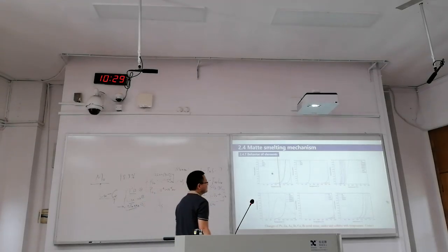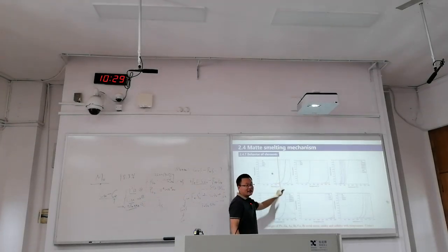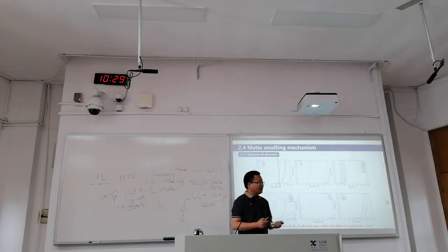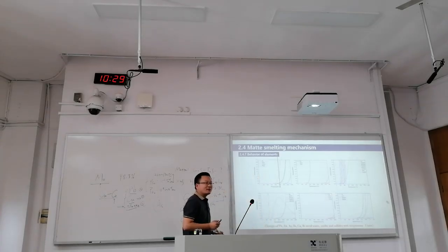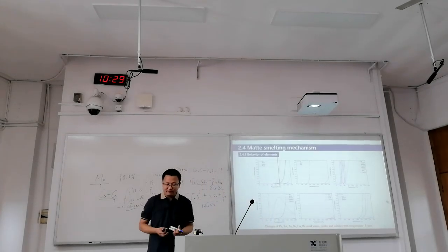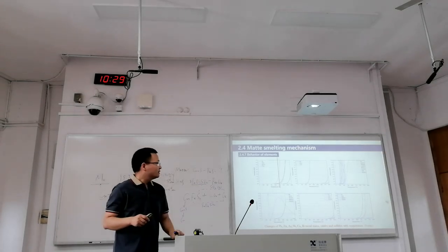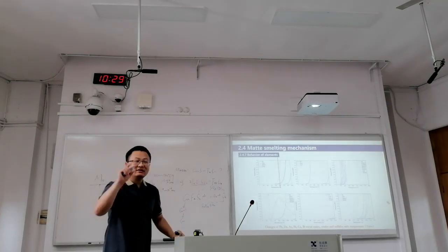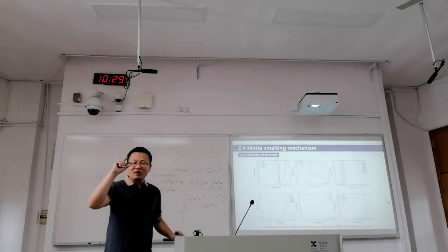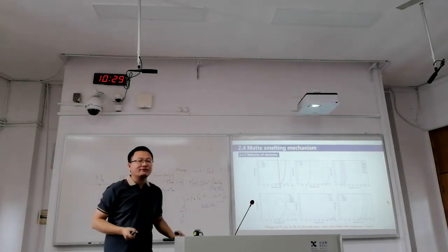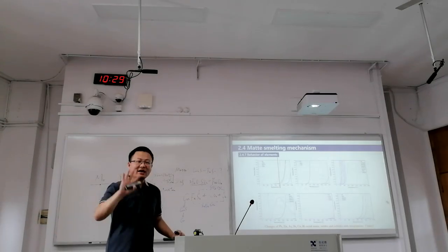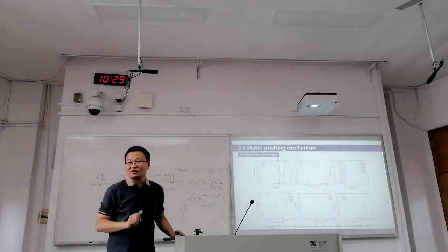And so does some oxides. In the future, some of you may have more information about the lead industry. In the copper smelting process, the dust formation is around 4%. When you are adding 100 kilograms of copper concentrate, you are getting 4 kilograms of dust.